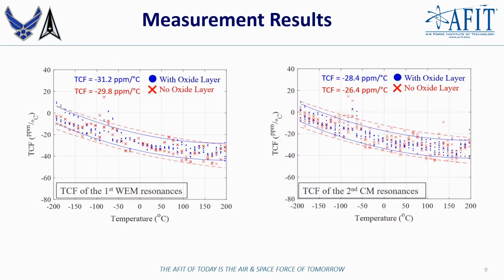So here, this graph shows the temperature coefficient of frequency measurement results for the resonator over a wide temperature range from -200 up to 200 degrees Celsius. On the left here, we have the TCF for the first width extensional mode, and on the right here, we have the TCF for the second contour mode. The blue points represent the resonators with an oxide layer, while the red crosses represent the resonators without the oxide. As we can see here, the TCF for both configurations follows a similar trend, demonstrating that the addition of the oxide layer does not significantly alter the TCF across the temperature range.